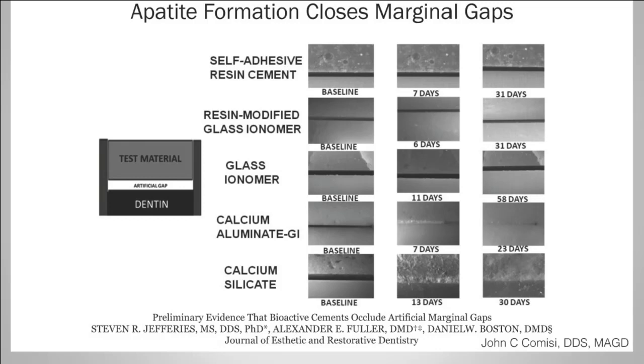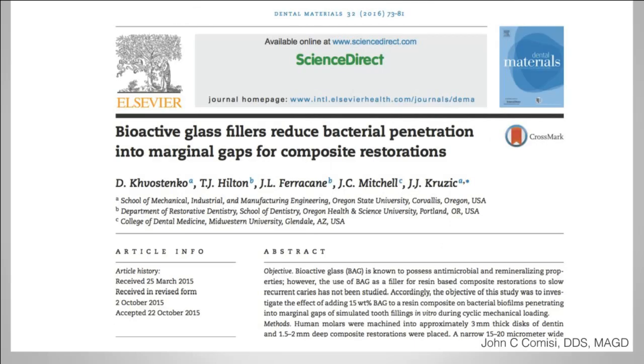So they created a gap and then put the material on the substrate to try to see if apatite could form over the course of time. The top three materials, even after 58 days, did not create any type of apatite. But we can see that the calcium aluminates and the calcium silicates, after about 20 to 30 days, really closed and sealed the tooth spectacularly. So that's a really exciting thing, and that's really what bioactivity is now defined as.